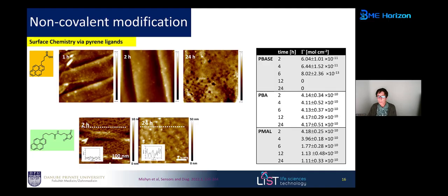If we then compare this to the acid form, you also see that after 2 hours, you easily have already some of the structures present. With 24 hours, we are seeing actually already holes and a more 3D structure. Here again, when we put ferrocene on it, we easily can, even after 24 hours, still see ferrocene coupling.